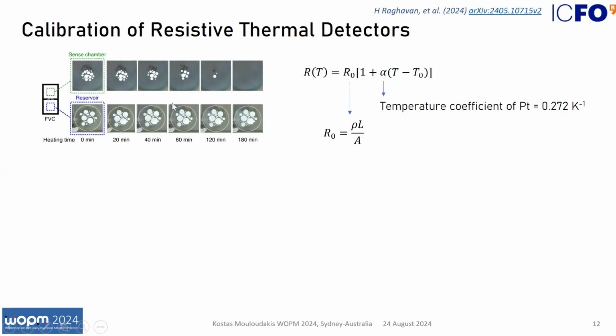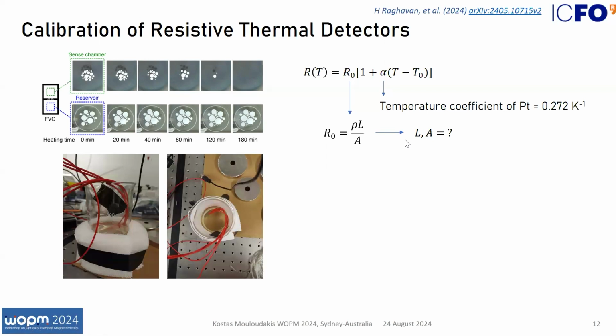To characterize and calibrate our temperature sensors, we use this formula, which relates the resistance of the sensor to the temperature. There is a characteristic resistance R0 at room temperature, and this alpha here is the temperature coefficient of platinum. We can see that this characteristic resistance depends on the length and the area of these current traces, which we cannot really know very well in our case. So we decided to measure and calibrate our sensors.